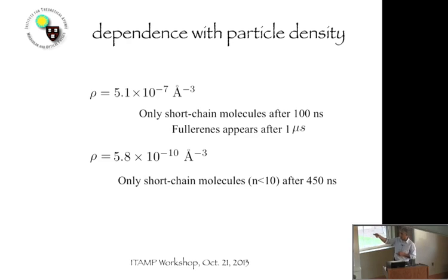And fullerenes appear. We did these sorts of simulations up to very long times. Long here means several microseconds, which in computational time is enormous, given that the time mesh size we were using was about 0.1 femtoseconds. And fullerenes appear after about 1 microsecond in this case.